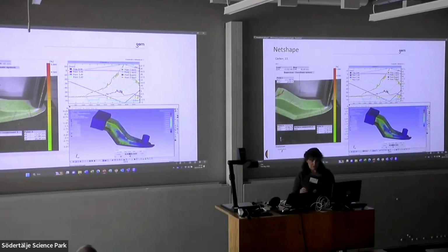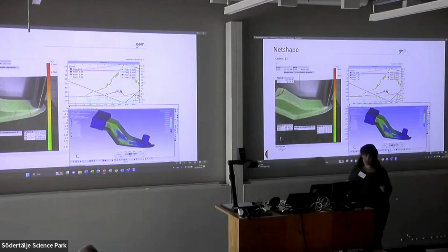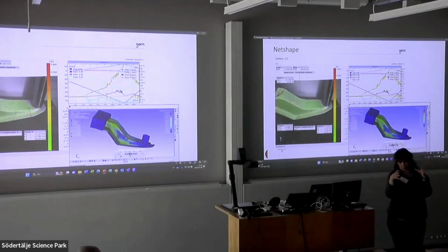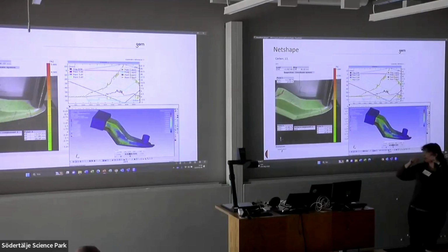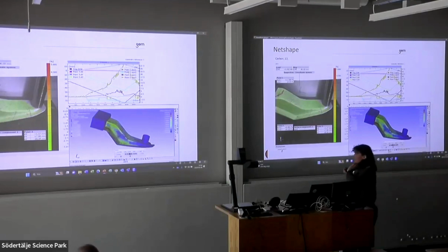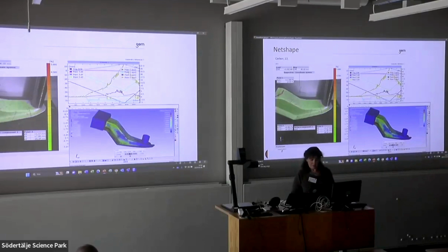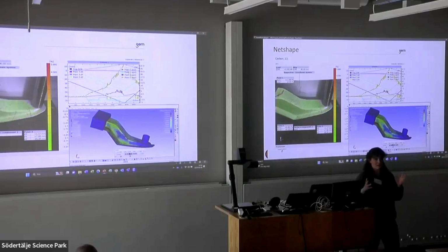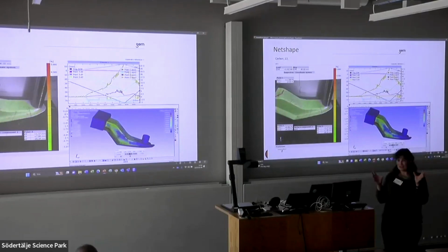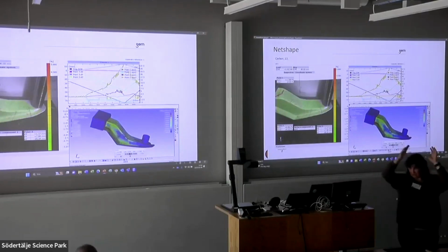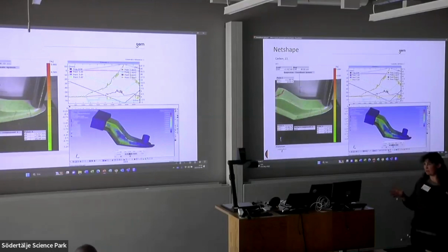This was done for the net shape. The net shape means that the material drapes over the tool, and that was compared to a block where you just put a stack on top. One of the biggest problems also is that actually the SMC looks like it's working. If you put the charge pretty much anywhere, you can push the SMC down and it will pretty much fill up your whole mold.